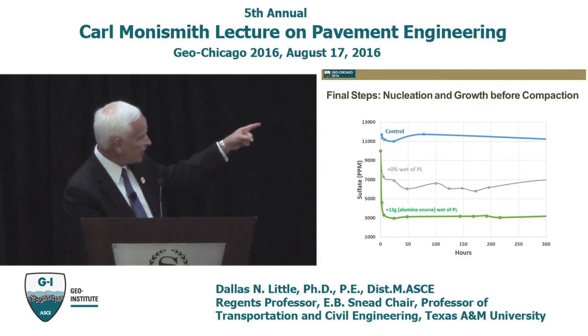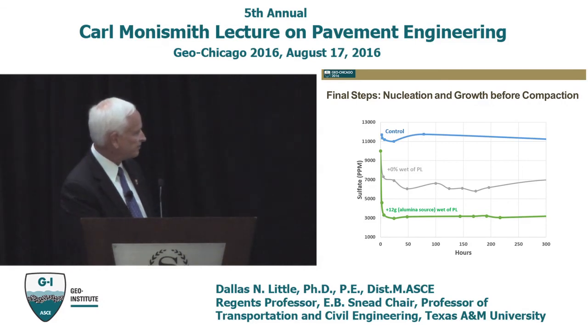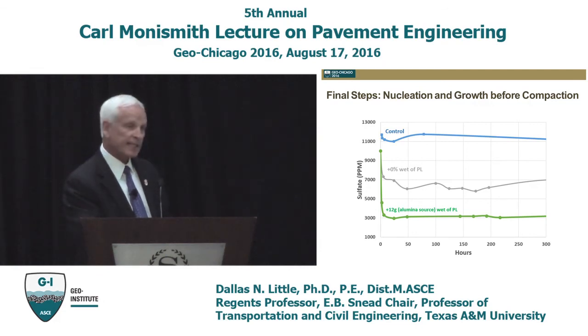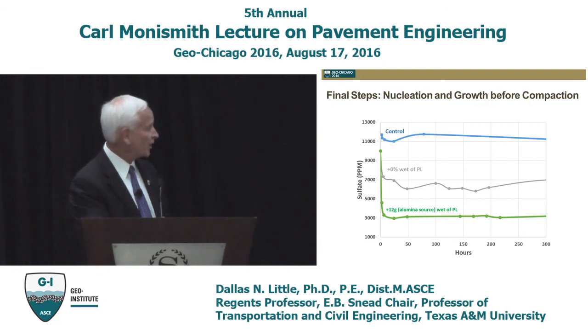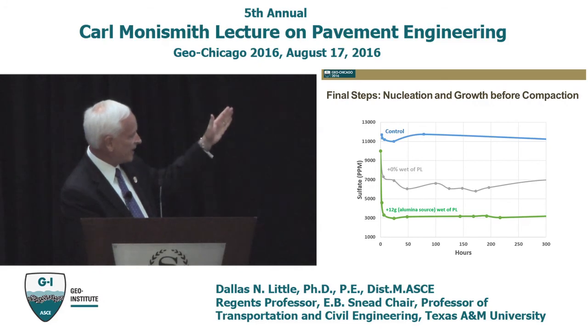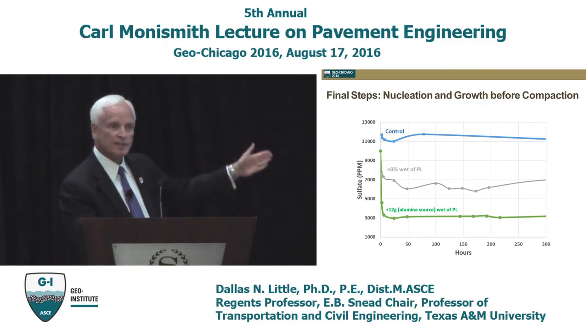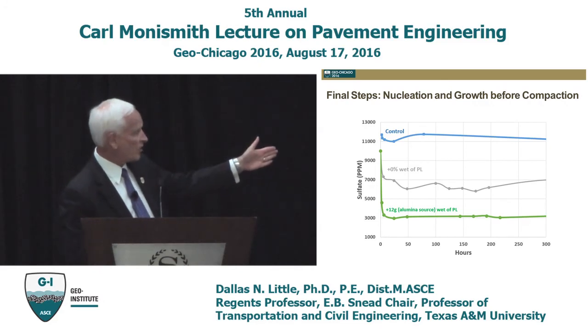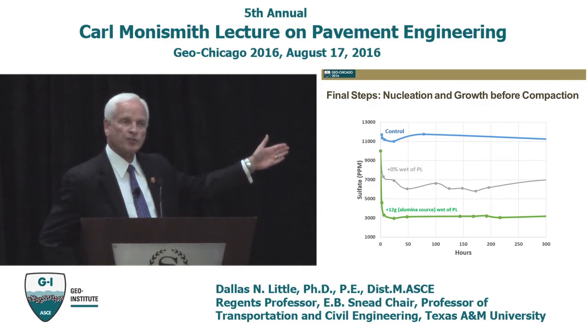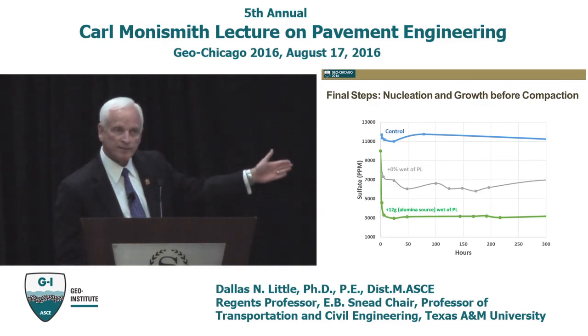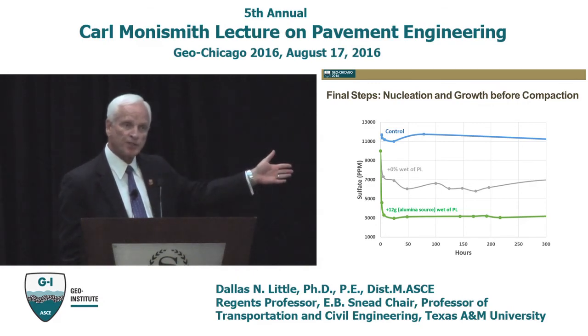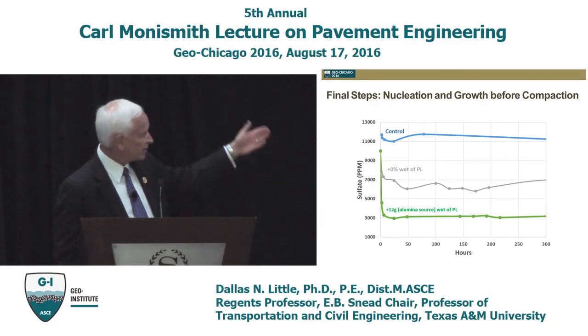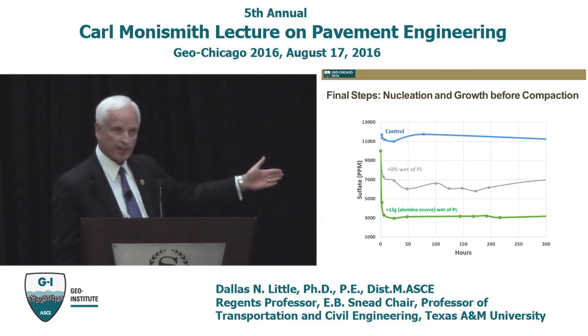And so what you see here is by adding about 12 grams of that alumina, and I can't remember what the size of the sample was offhand, but it really did activate the process. Now what's going on here to cause the water-soluble sulfate to drop? If I get down to 3,000 parts per million, I'm pretty safe. If I compact it at this point, I'm pretty safe volumetrically. So what causes it to drop to that level?